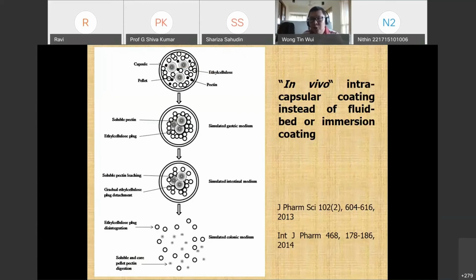Now, in these studies, we create in vivo intracapsular coating instead of fluid-bed or immersion coating. So we have our cancer therapeutic pellets being coated in the body instead of being coated using a machine on the bench top. Let me go through the design briefly. First of all, we load the drug into pectin-rich pellets, and we mix the pellets with coating powder, which is constituted of hydrophilic pectin as well as hydrophobic ethyl cellulose. The mixing of pellets and coating powder is done in a hard gelatin capsule.